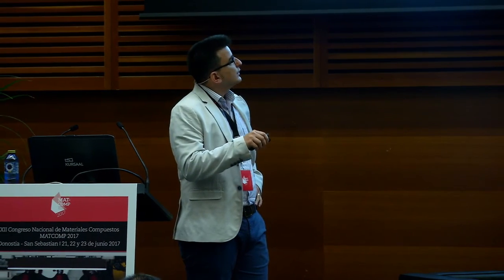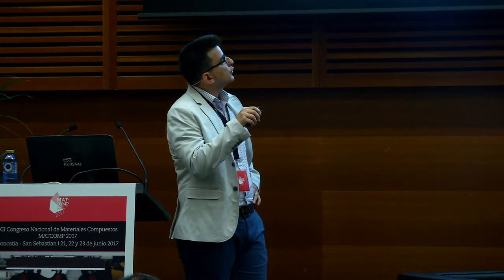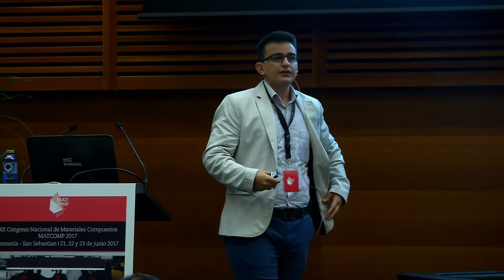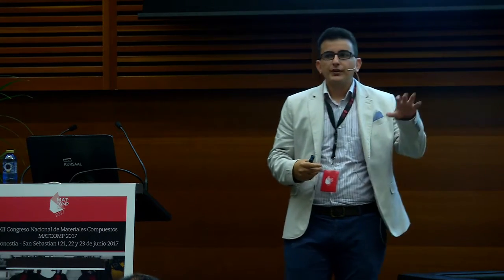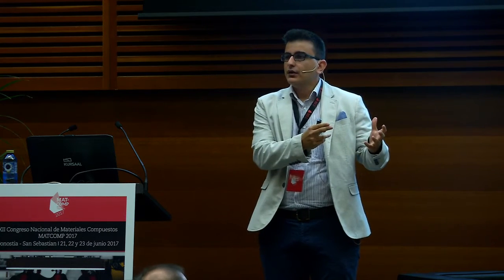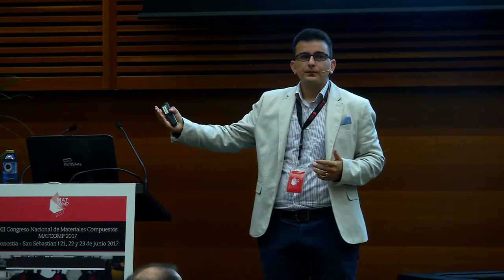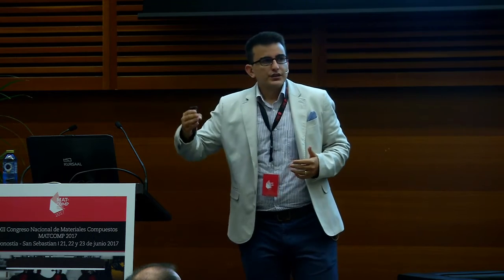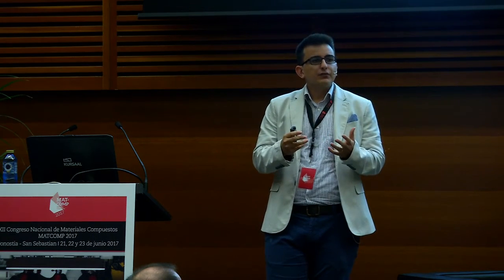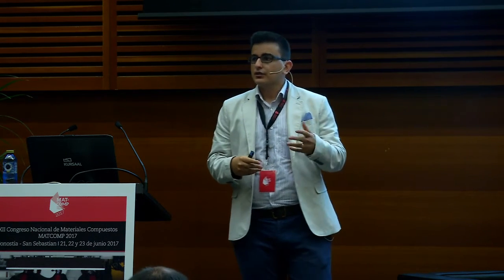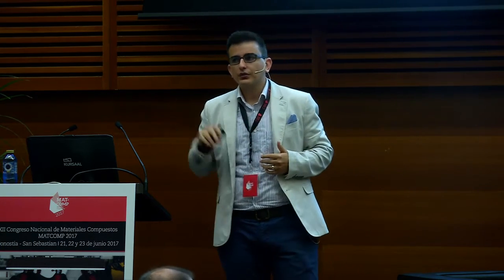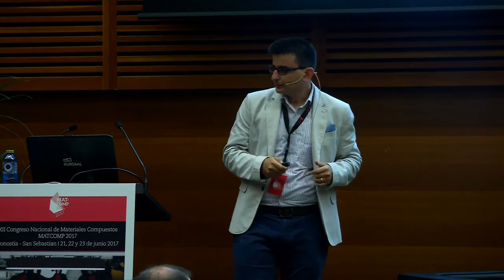And using the simulation platform, actually we can, for instance, investigate the effect of total volumetric shrinkage of the resin material on the final warpage. So this is very practical information for industry, such that they can modify their resin systems and see their effect on the dimensional stability.